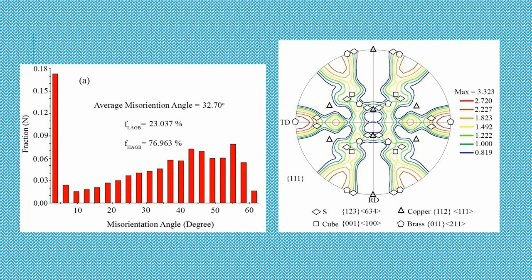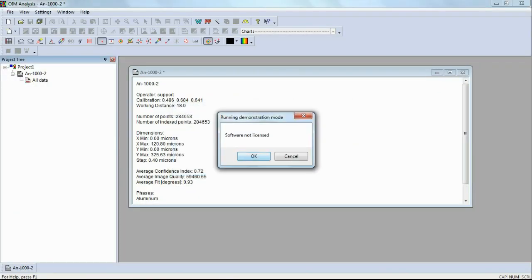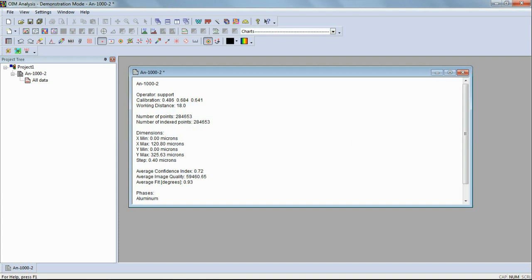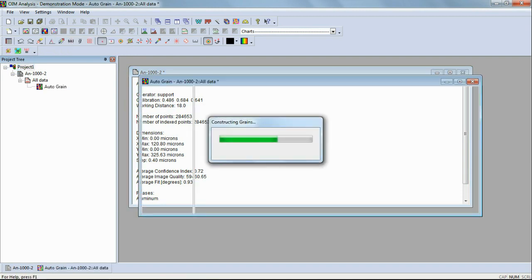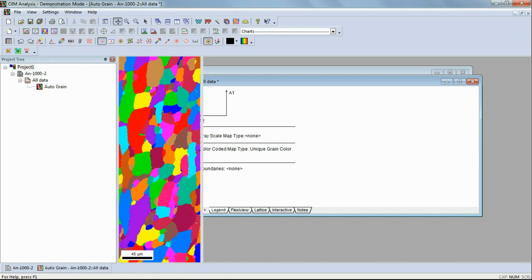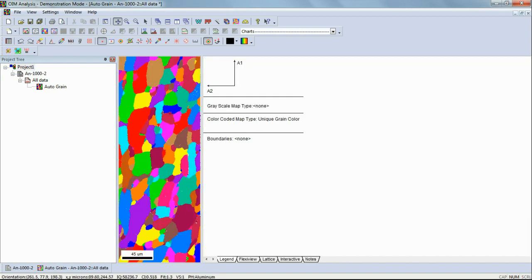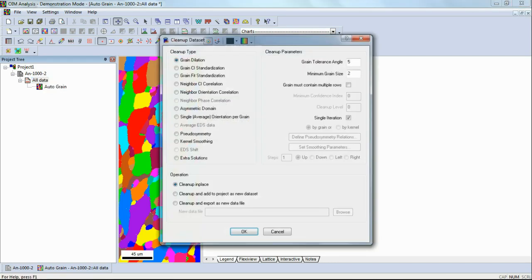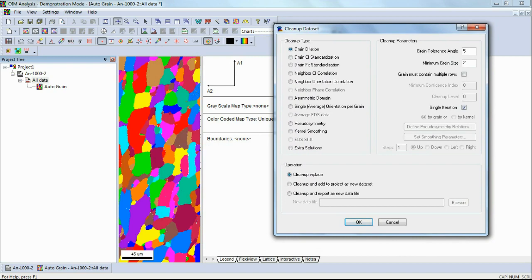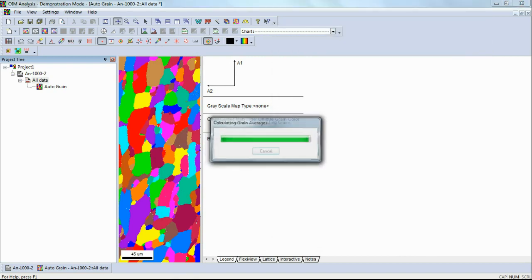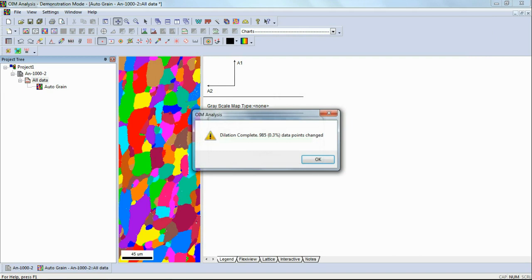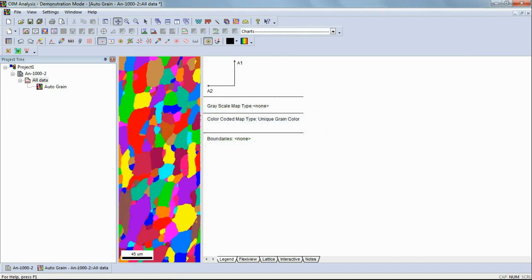First, open the analysis file in the program. Here I show you the analysis of the annealed aluminum EBSD. This app is highly user friendly. At the top of the page there are different options to create different maps. One of these maps is the map of the grains with different colors for each grain. This map shows only the grains to detect the grains apart. Each grain has a different color than the surrounding grains. EBSD analysis is based on calculation. For this reason, there are disruptions in the maps. To improve the result, right click on all data and click clean up. In this case, the maps will become cleaner. Right-click on the map can change the scale bar.